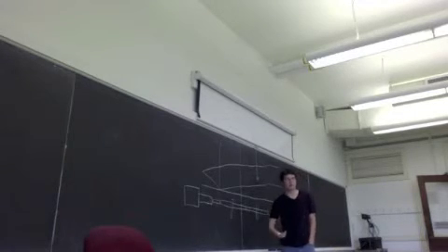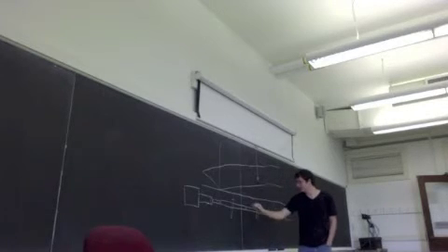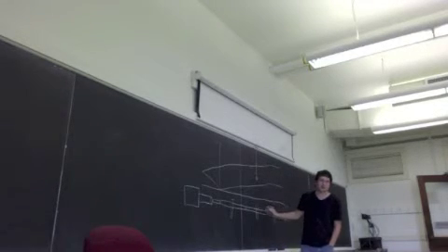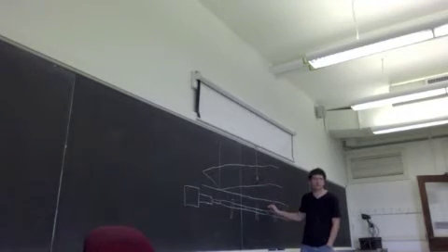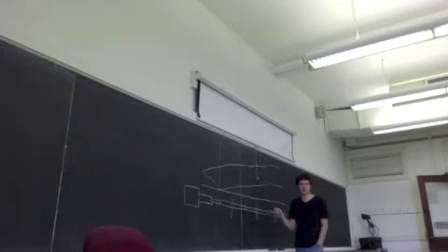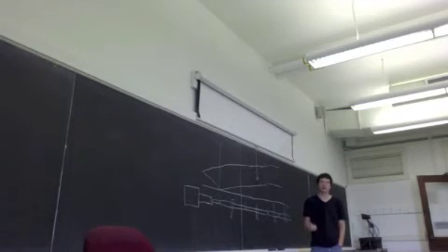Now, if we record all these pulses, we have strains at various times. Since we know these lengths and the wave speed in the material, as well as the strain, you can shift these pulses to the sample, convert for the difference in diameters, and then use Hooke's law to get stress. And what you end up with is stress, strain, and time in the sample instead of the bar. And now you can use that information to also get strain rate.